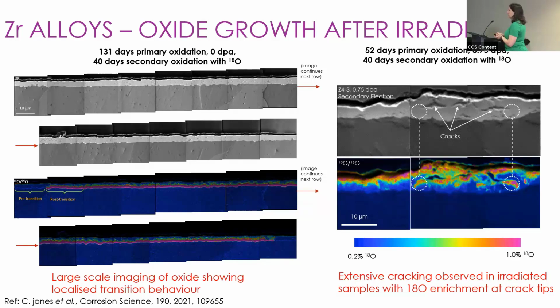But if we look at this adjacent region here, we can see that this has not incorporated any oxygen-18. This bit of oxide here, and actually this bit of oxide just over here, has not yet undergone that transition. So we can see individual events happening in some cases, where you can see the penetration of the oxygen-18 and spreading out of the oxygen-18 along the metal oxide interface. So we're starting now to get temporal information from our NanoSIMS imaging. You wouldn't be able to determine this just by looking at the structure of the oxide. That oxide is probably very similar in structure to what's above it, and chemically identical. So by using the oxygen-18, you can actually pinpoint exactly which bit of oxide is growing at any particular point in your experiment.